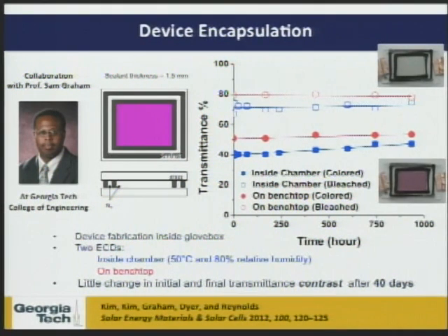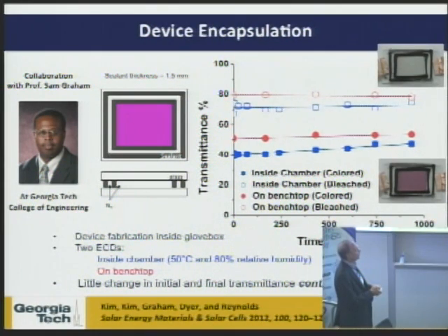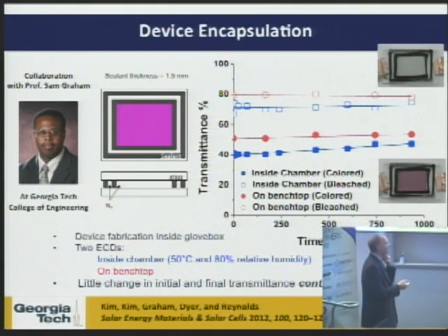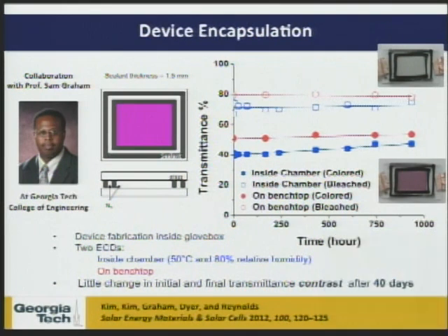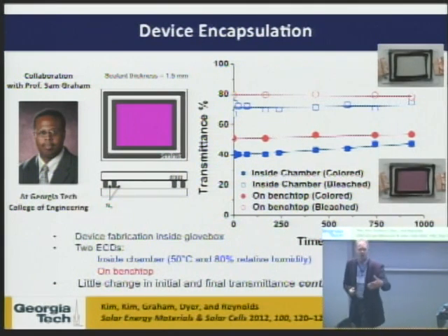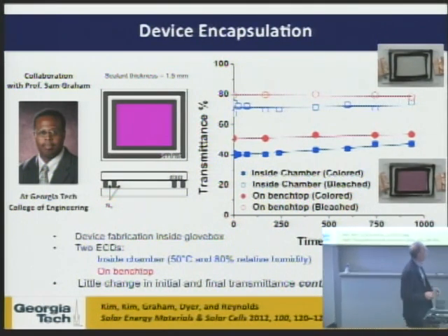And what you can see here are some photographs of the devices and the conditions in which these devices were held for 40 days. Inside a chamber at 50 degrees C and 80% humidity, you can see that the transmissive state, in essence, held for that 40 days, and there was a little bit of loss of color over that 40 days in the magenta state under those conditions. And so we have really quite nice stability at relatively harsh conditions in these laboratory-built cells. And so we feel that the cells themselves, in terms of moving ahead towards window-type devices, are potentially useful there.